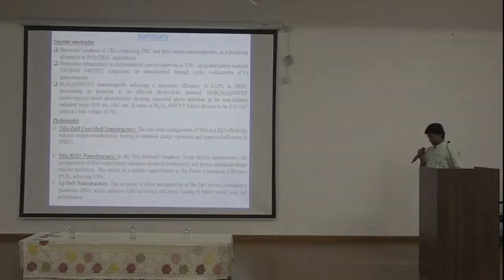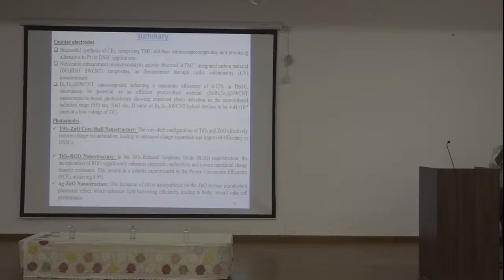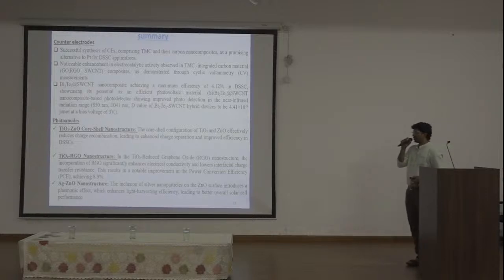In summary, for the counter electrode part, when the transition metal chalcogenide is composited with reduced graphene oxide, it is not only providing electrical conductivity but also providing higher active sites for more electrolyte to make contact with the counter electrode, improving the electrical conductivity and also the electrocatalytic activities.